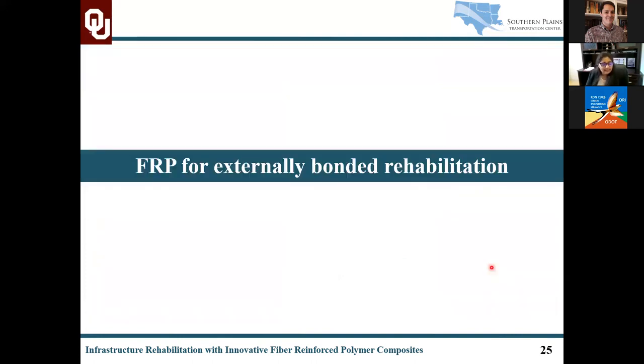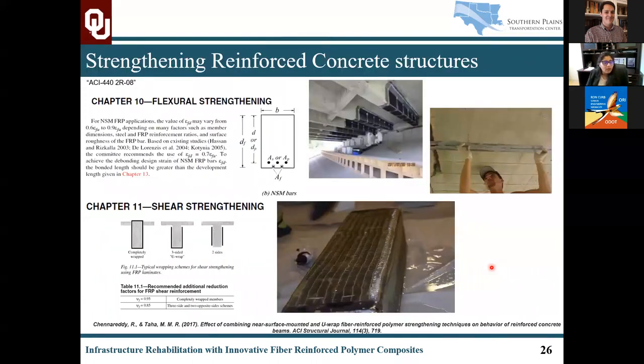If we look at externally bonded rehabilitation, a lot of future in this direction as well. We see ACI 440 that governs the flexural strengthening of reinforced concrete beams and the shear strengthening of reinforced concrete beams. The flexural strengthening with near surface mounted FRP, where a saw-cut groove is made on the tension face of the beam. The groove is first half filled with epoxy and additional FRP reinforcement is placed in this groove, and then the groove is completely filled with the epoxy and left to cure.